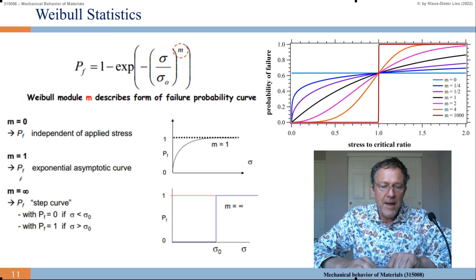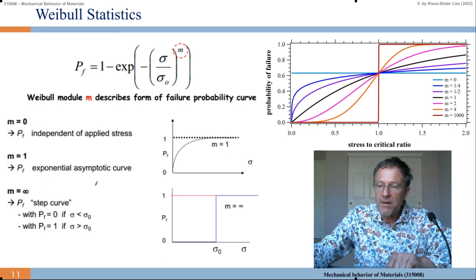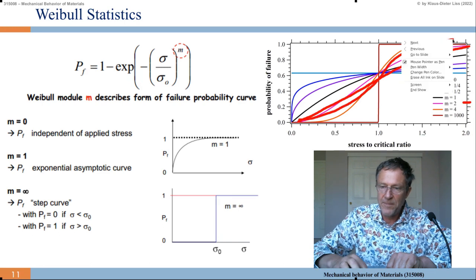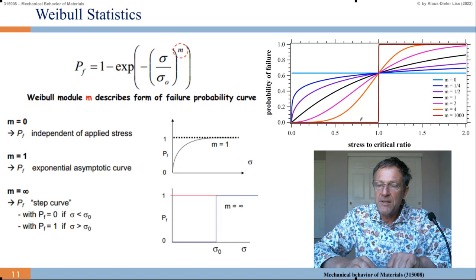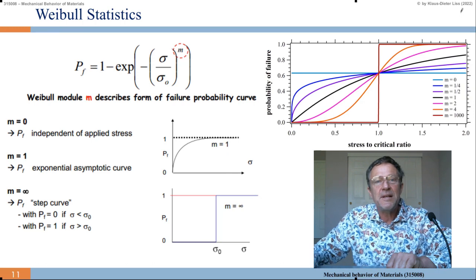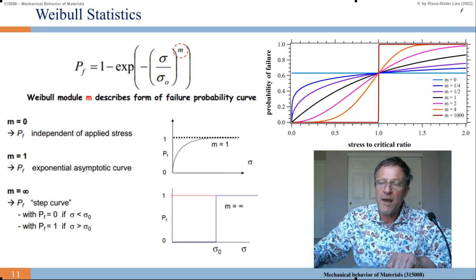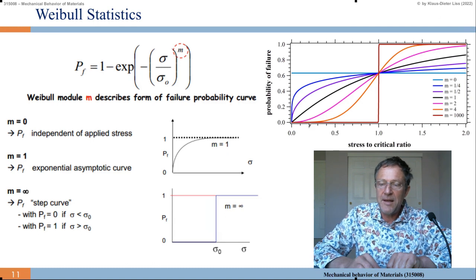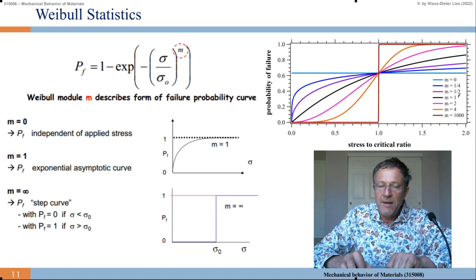Now, if we make m larger, so m equals 2 is the pink curve here. We see it increases. m equals 4 becomes this red curve, and m equals 1000 becomes this very steep curve. It resembles a little bit the error function. It's not exactly the error function, but it resembles it. It means it goes up in this way. And how it goes up, the width of going up, depends on the Weibull modulus m, so on the exponent m in the exponent of the exponential function.